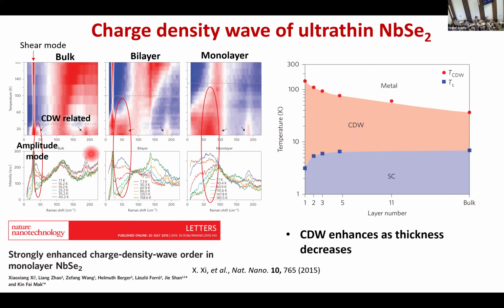This mode they didn't understand at that time. However, it also disappeared around the same temperature. So then they call this also CDW related. So one can see that these features, they can extend to much higher temperature when we go to, for example, bilayer, and for monolayer, and it goes to even higher temperature. Also, although I would say that by looking at the data, I cannot really so confidently say that this can really extend to this high temperature, but you can see that at least it's enhanced from bulk to a monolayer. So this is why they plot this phase diagram by saying that when you reduce the number of layers, then the charge density wave gets enhanced. So this is also about the dimensionality effect.